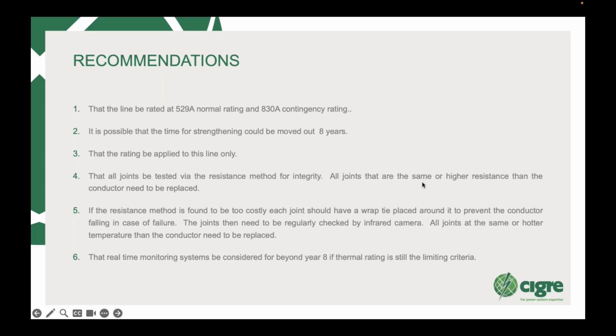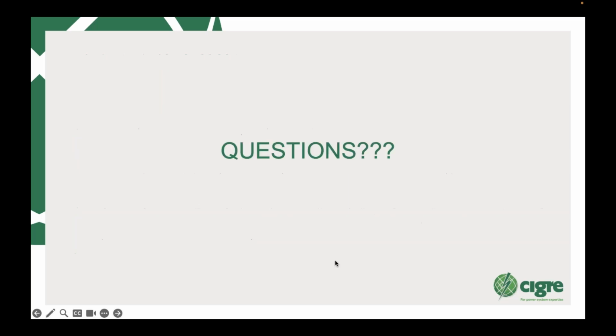And you'll see in the Cigre document it says how much less and how you actually determine it: you measure the resistance on the conductor and the resistance across the joint. And the joint must be a certain percentage less than the conductor, otherwise it must be replaced. If it's not replaced, what you can do is put a wrap around the joint so that if it does actually fail, it will not drop the conductor. So, as we've mentioned here, a wrap tie is placed around to prevent failure. Joints need to be checked regularly, and all joints at the same or hotter temperature need to be replaced, especially on your jumpers where you could get a failure. So for real-time, we said we could use real-time monitoring systems. Over 8 wasn't necessary at the time.